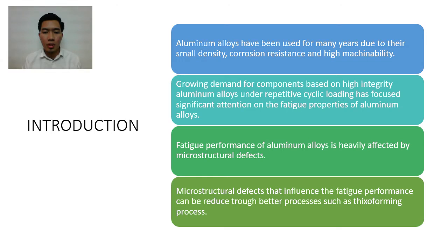But there is a problem in the area of fatigue, where the fatigue performance is heavily affected by microstructural defects. These microstructural defects that influence the fatigue performance can be reduced through better processes such as the Thixoforming process.